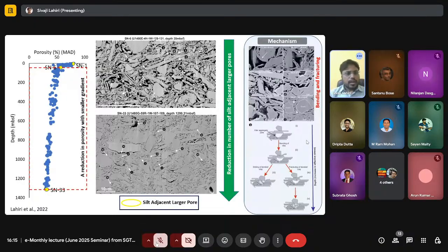Now, let's try to concentrate on the samples of 30 meter to 1300 meter depth. Now, here in this depth range, we observe small reduction in porosity, or maybe I can say reduction in porosity with smaller gradient. Now, this is the sample SN6 from 28 meter depth. You have already observed it in the earlier slide. And this is the sample SN33 from 1300 meter depth. You can see how the microstructure of this sample has changed with increasing depth.